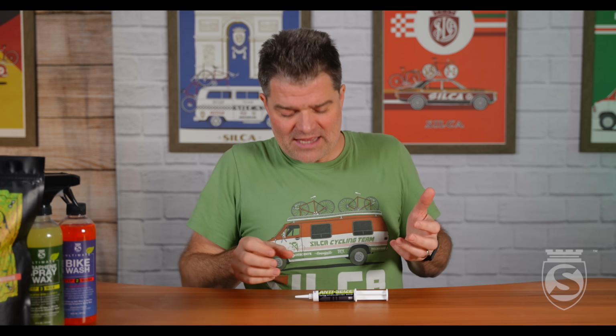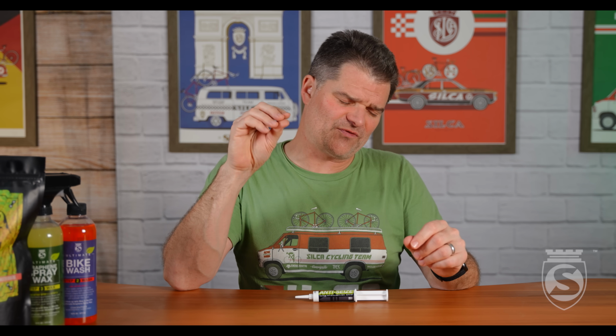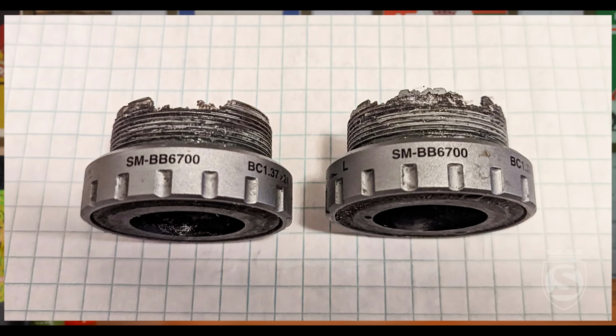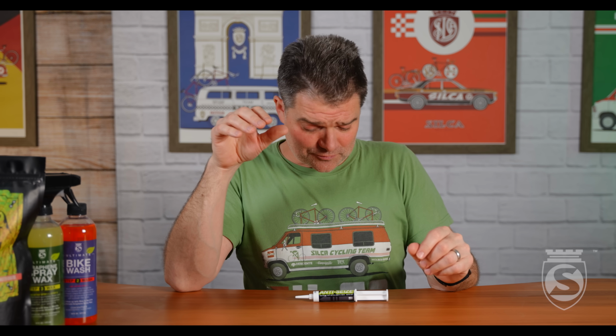The same thing happens in metal, and this is why for years people have gotten aluminum fasteners seized into titanium frames, titanium seat posts frozen into carbon frames, titanium seat posts into aluminum frames, you name it. People have had issues with it. And that is typically, or almost always, this galvanic corrosion problem. Aluminum seat post into carbon frame is a classic one. You sweat on it for long enough, especially if it's on your trainer and it's seeing continual sweat,